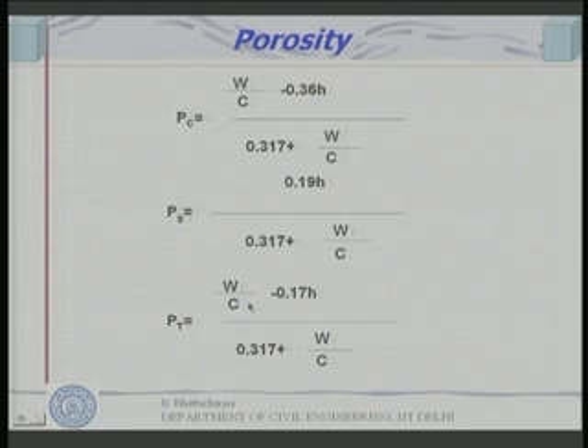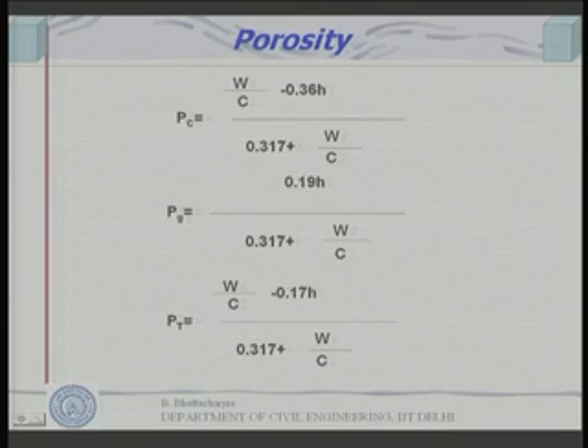Now, what is important out of this is that if you have a higher water to cement ratio, capillary porosity will be more. Physically we have understood this because the volume occupied by water in the original water cement system would be high and will not be filled in by hydration product. So the more water with respect to the cement, the more capillary pores. Gel pores are simply a function of the degree of hydration. The more the degree of hydration, the more gel pores, because they are associated with the solid product of hydration, the CSH gel. The more CSH gel, the more gel pores. It is inherent, it would be there.